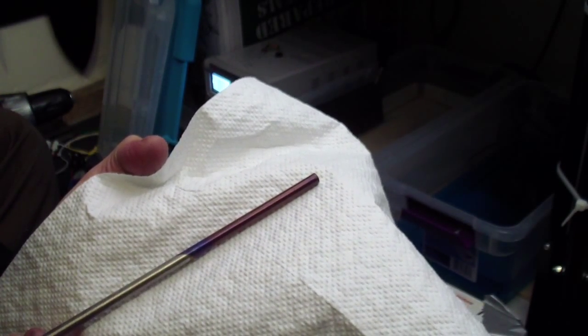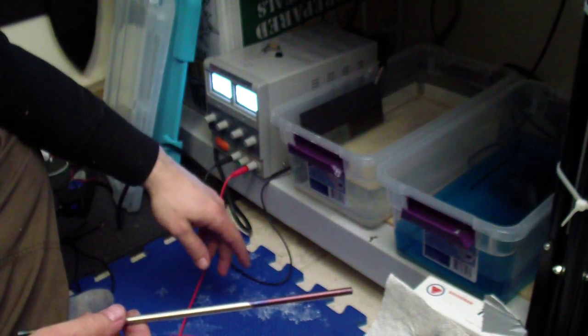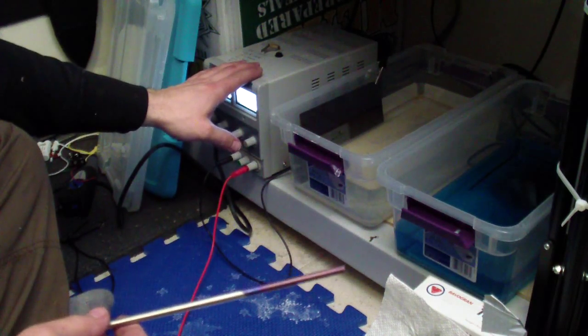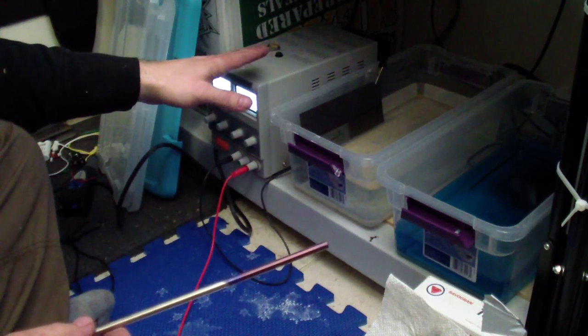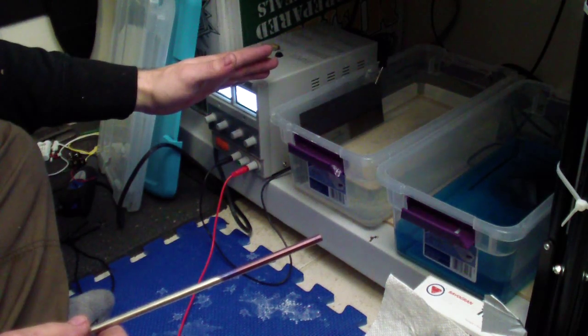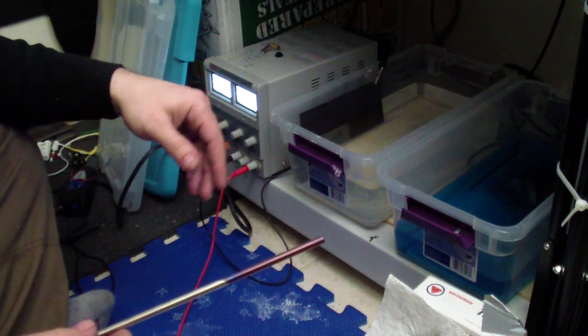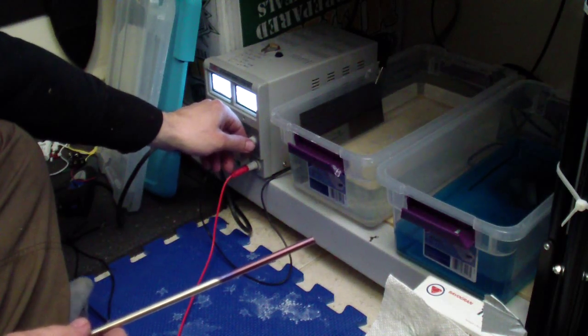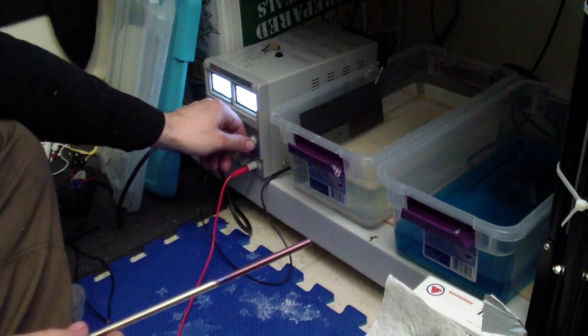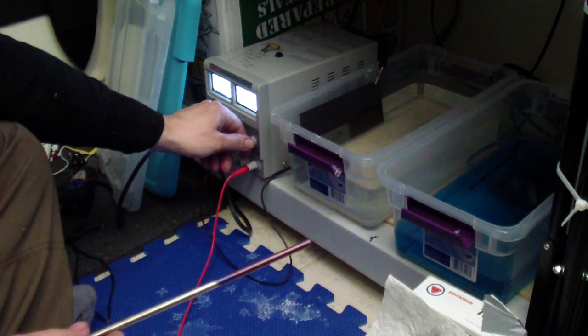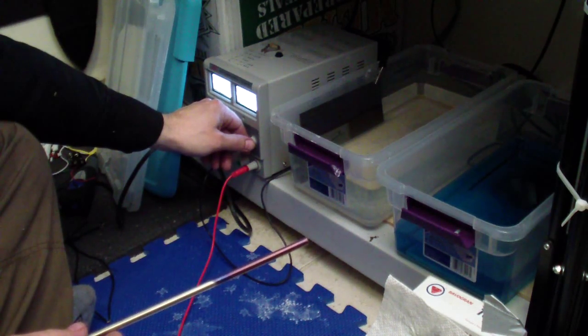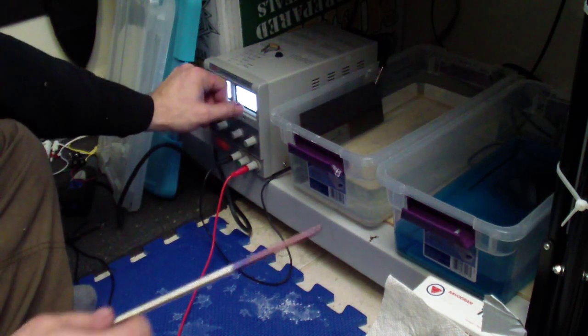The better ones you can also buy the whole pre-made kit. It's actually from zero to 120 and that one gives you more colors towards the end. You get green and kind of like a pink. Look at that, this one is 25.5 volts, that's the really nice blue I like.